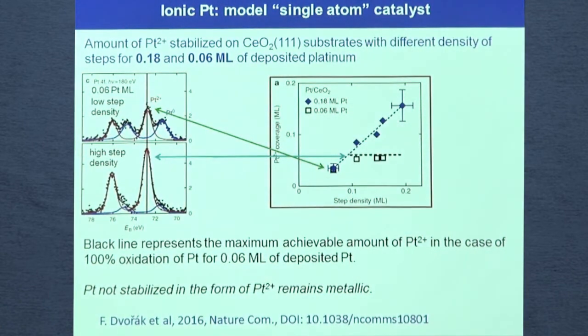Well, and now returning back to the first case of stoichiometric surface with low step density. You can see that in that case, we deposited two different amounts of platinum at the surface. For 0.06, you can see that we change the density of steps. This is the low, this is the highest, and now we perform the experiment by changing density of steps.